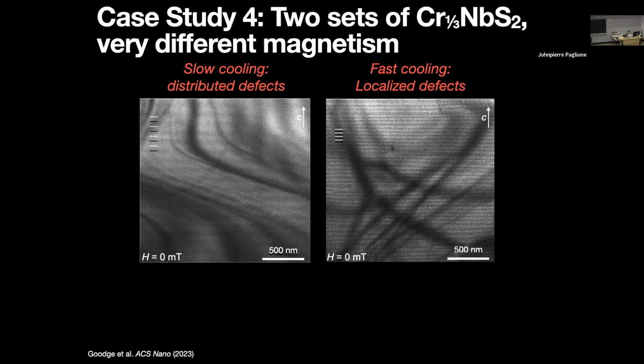And then they might end up crashing into each other and creating domain walls that you don't want between slightly offset 2x2s. So instead, what you probably want to do is, as you're saying, rapidly go down to where you have a root 3 by root 3, and then warm up to that sweet spot for the 2x2 and allow those nucleated domains, which are hopefully far apart from each other because there are very few, to slowly grow out. That's the guiding principle maybe, but we'll see. It will depend a lot on the intercalant too. I think there are some intercalants where that's easier to get to work than others.